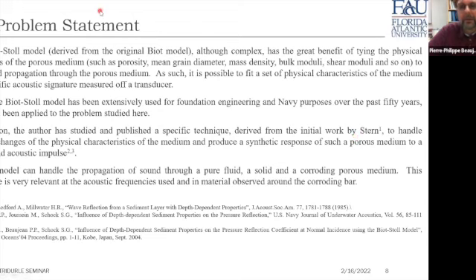Now, to conclude with the problem statement, the Biot-Stoll model, which is actually at the root of what I am presenting here, although complex, has a great benefit of tying the physical properties of the porous medium, such as porosity, mean grain diameter, mass density, bulk and shear moduli, and so on, to the sound propagation through the porous medium.